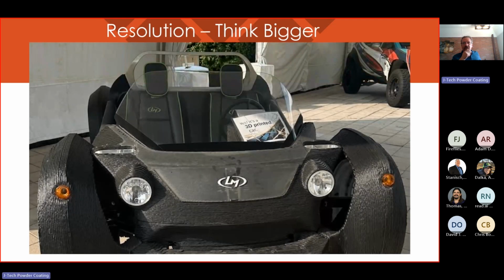Here's the finished product. There was some machining done to fit the lights and other hardware and to clean up the hood, but the overall surface was left as printed to highlight the manufacturing process. Nearly all models completed with high extrusion rates are going to be machined for cleanup. They are really a near net shaped part.